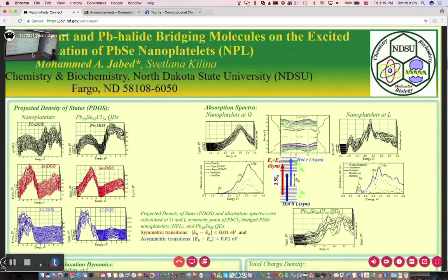similar with the time. So it's not changing. It's almost featureless, like the plane absorption spectra of a bulk system also. But at the L points, if you look at this dispersion curve, they have a subgap at the L points. And due to this subgap, in the L point absorption spectra, they have one low energy peak and a high energy peak around here.